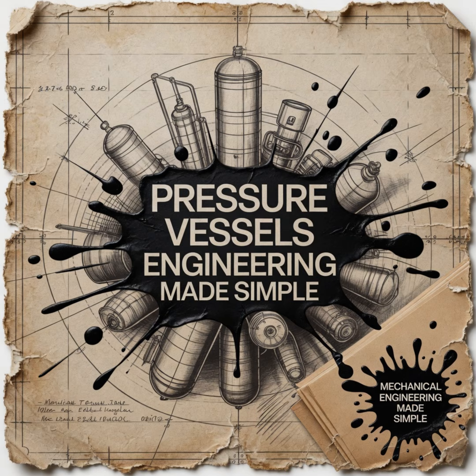Oh, I see where this is going. Yeah, in mechanical engineering, any sharp change in geometry is a stress riser. It takes the normal, safe stress flowing through that massive steel wall and concentrates it exponentially right at the microscopic tip of that pit. So it multiplies the stress locally. Massively. And that spike in localized stress will initiate a crack. Once the crack starts, the pressure inside the vessel rips it open instantly. The vessel fails catastrophically. It basically unzips long before the pit ever drilled all the way through.